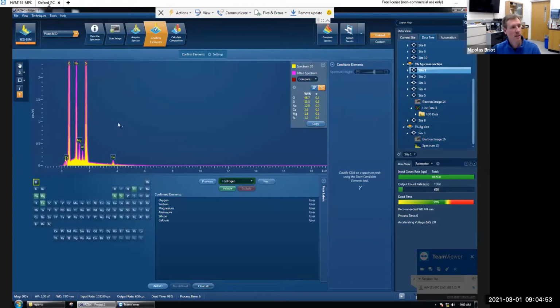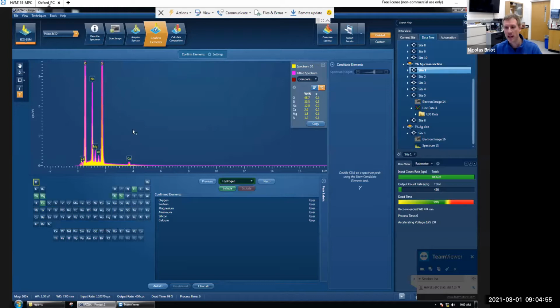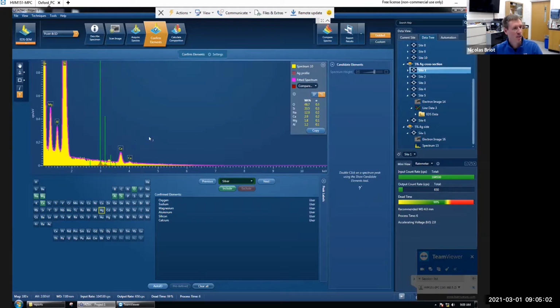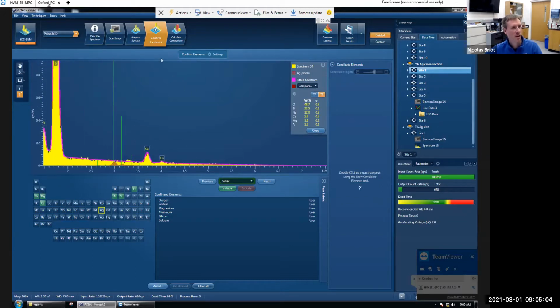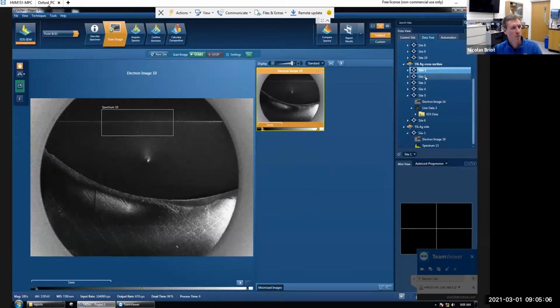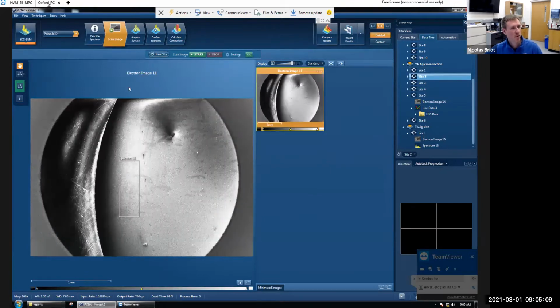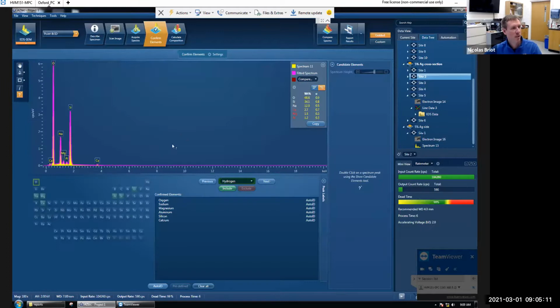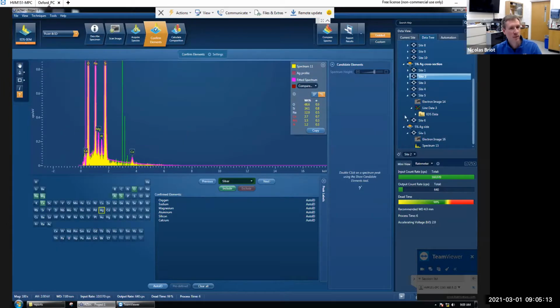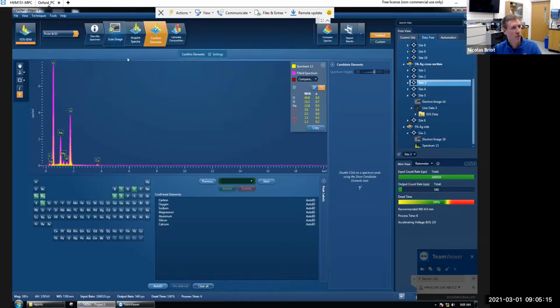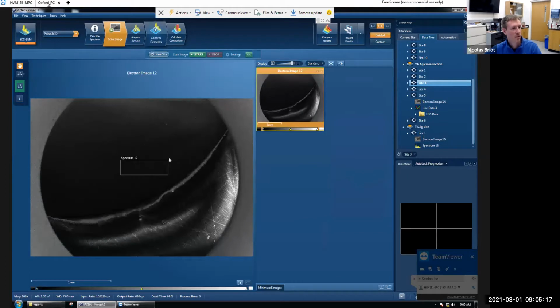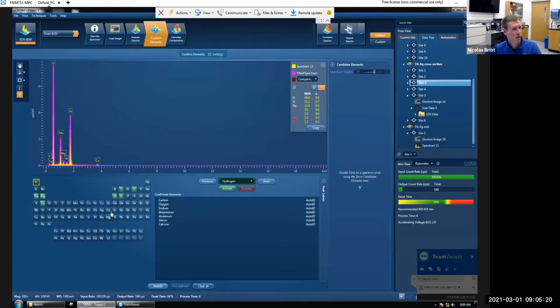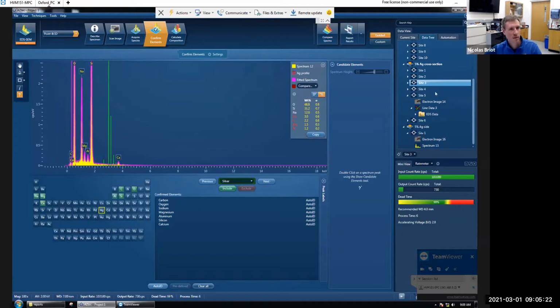Remember, that's an EDS spectrum. It shows you the energy of the X-rays that we are capturing coming back from the sample. And if you look over there where silver should be, there wasn't anything clear on this one. Went to a few spots, another one a little closer to the surface, maybe 0.5 millimeter. Again, we couldn't see silver. So we did a few of those closer to the surface. Again, nothing visible really as far as silver goes.